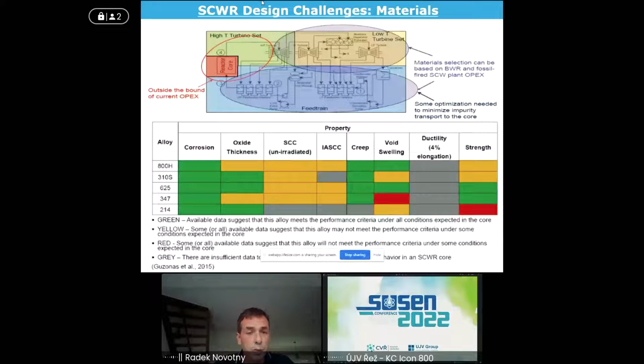and so on. If you look at the selection of materials that has been done for these critical components, from the corrosion point of view and from other degradation mechanism points of view, the most critical ones were identified and a kind of classification has been done. But please don't take it as a complete classification. Even if you look at corrosion, which seems to be a pretty much solved issue, in reality it's not. It's more or less knowledge gathered in the past 20, 30 years. And from that, we a little bit optimistically said that we have some corrosion resistant materials, but we didn't evaluate all the materials which are commented on later.